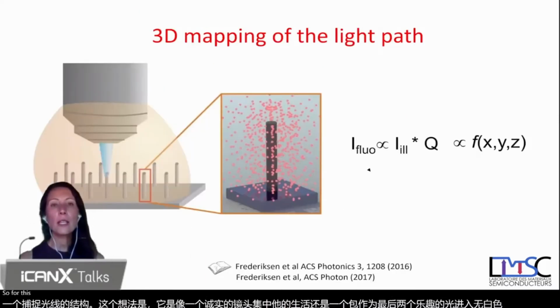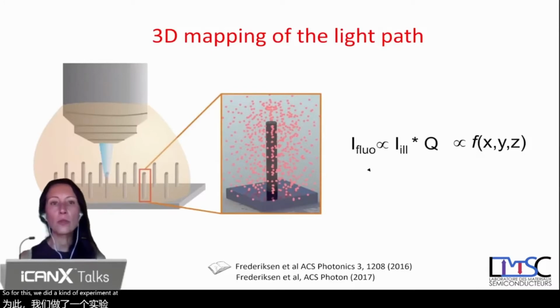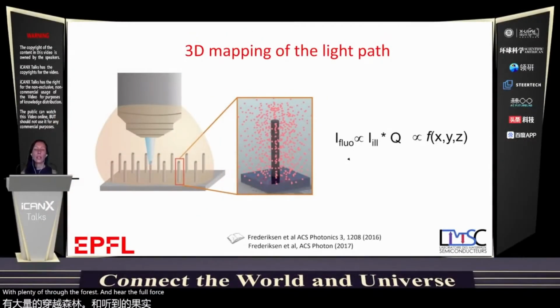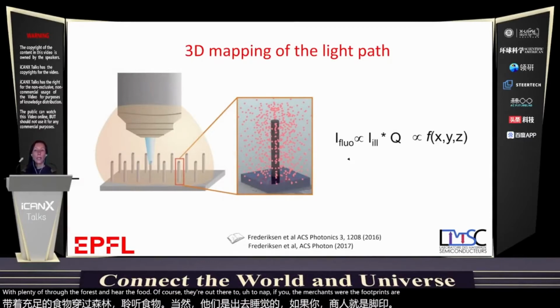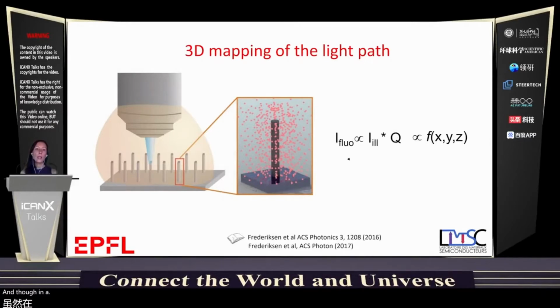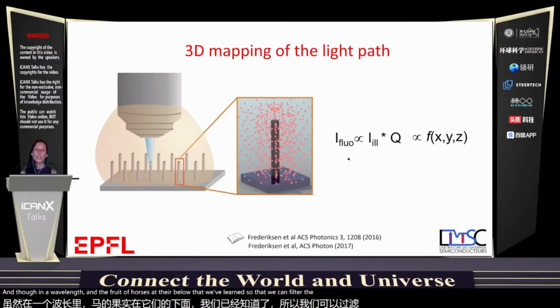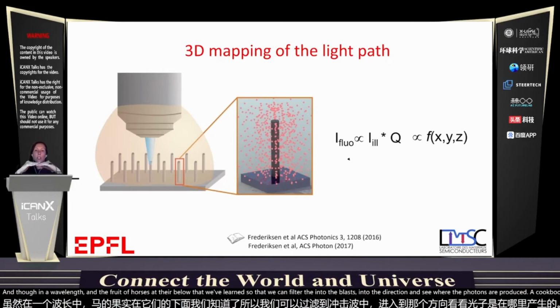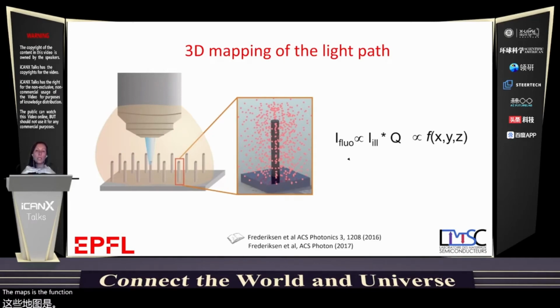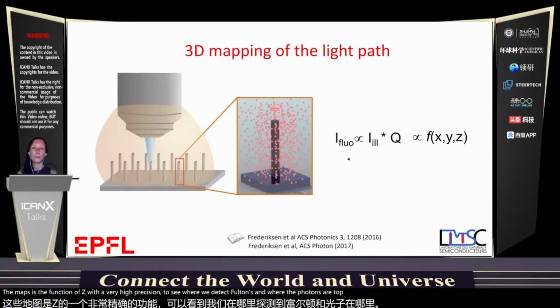So for this, we did a kind of experiment that is quite original in my sense. So we put the nanowires in a liquid solution with plenty of fluorophores. And here the fluorophores are there to map in 3 dimensions where the photons are. So we send some photons at one wavelength, and the fluorophores emit below that wavelength, so that we can filter the incident light in the detection and see where the photons are. We use a confocal microscope, so like this, we measure the map as a function of z with a very high precision to see where we detect photons and where the photons are at all.